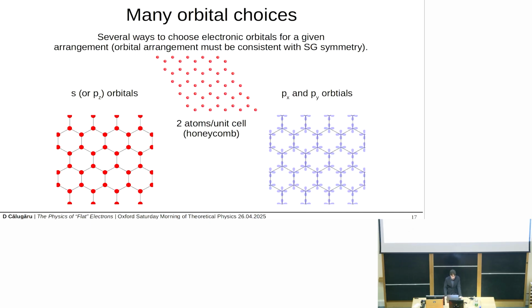In both cases shown here, I've chosen my occupied lattice sites to form a honeycomb lattice. On the left, we have s orbitals, and this should give you something graphene-like, with Dirac cones and symmetry-enforced crossings. However, on the right-hand side, we place px and py orbitals instead. They have very different symmetry properties. They point in plane, they will hybridize differently, and the resulting bands will behave very differently.